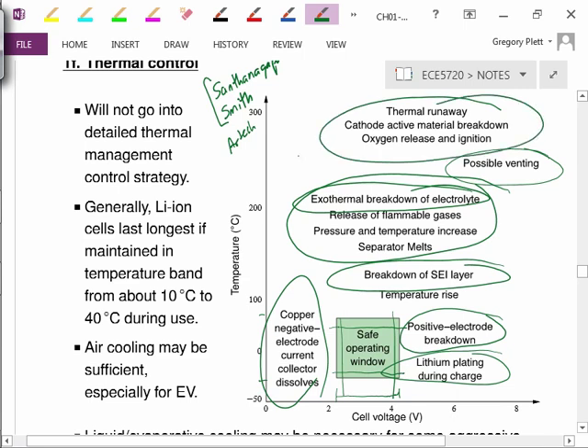Because of this exothermal breakdown, the temperature, once you reach a certain point, becomes self-sustaining, and you have what's called thermal runaway, and the cathode active material breaks down, not in the sense of dissolving, but in the sense of oxidizing, basically catching fire. The cathode materials, the positive electrode materials, are usually oxides, and there's enough oxygen in them to maintain any kind of combustion that has started. So even if you completely smother the battery cell at that point, there's enough oxygen internal to the battery cell to maintain a fire. So if you ever get there, you hope you don't, the fire extinguisher is only going to put out the secondary fires. It's not going to put out the battery fire itself. The battery fire is just going to run until there's nothing else left to burn.